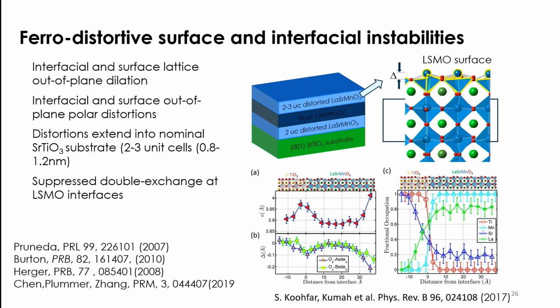But what we found here, which was significant, was that this effect was not just at the surface. There was a decay length of this distortion, which was on the order of 1, 2, 3, 4 unit cells. So if you count from the surface, there are about 2 to 3 or 4 unit cells which are distorted, which have this polar-like distortion. And then there were some other changes in the structure.